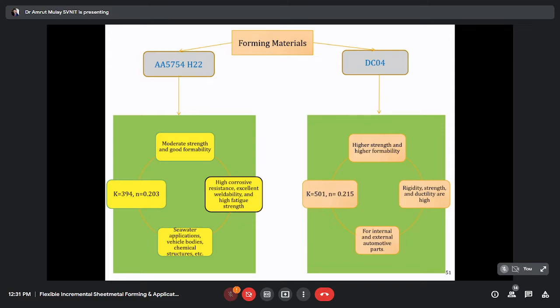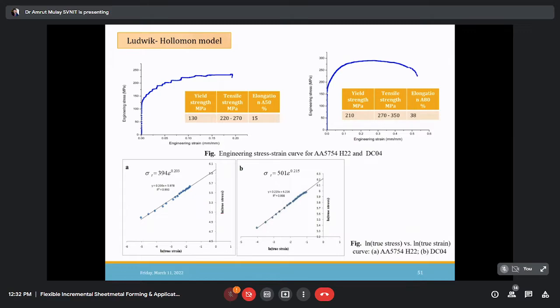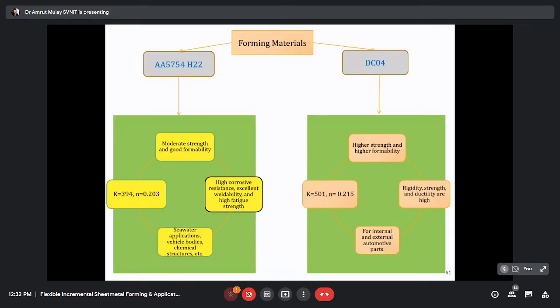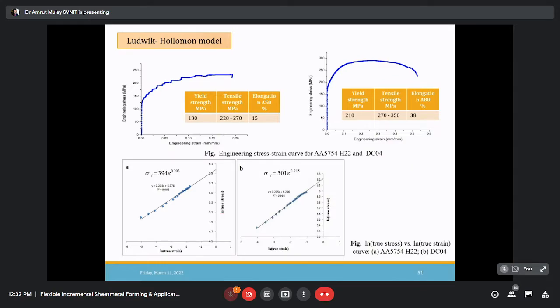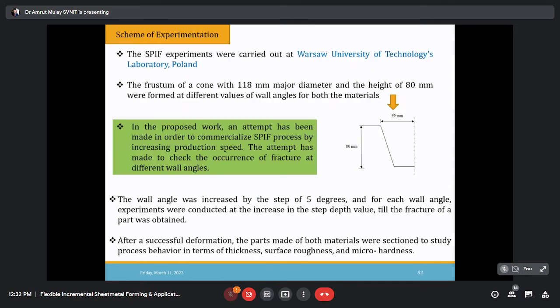That is one different technique. Say, for example, you have to do the curve fitting in Excel. So these are constant parameters using the Hollomon power law, right? You can see that the Ludwik-Hollomon model we used to fit the model. You can see the engineering stress-strain curve, and for the two different materials we then convert into ln of true stress. These are tensile tests we performed on these two materials. We got engineering stress-strain, and we got this ln of true stress and true strain. We got this value, and K and N values we obtained.